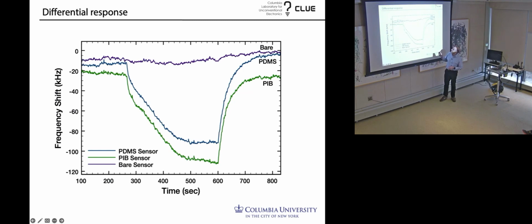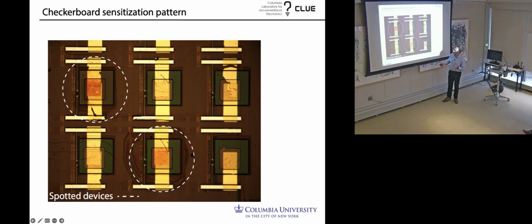So this is a bare surface with us pushing some vapors in. In this case, we're using toluene. Then we put a sensitizer, and we used a silicone, another polymer, that is able to grab on. In the presence of a sensitizer, it can then get extra mass that slows down the resonant frequency. And then you can use that, in principle at least, to make an electronic nose type system with different sensitizers, et cetera.